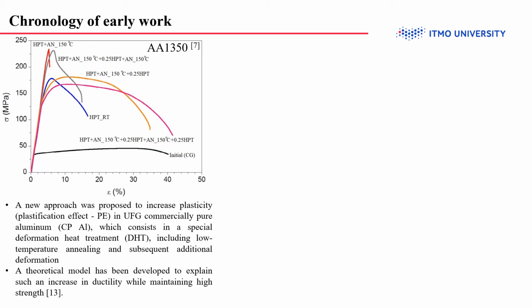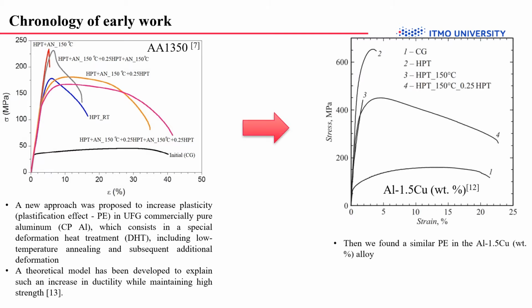According to this model, during the additional deformation, an additional density of extrinsic grain boundary dislocations is introduced into the structure of high-angle grain boundaries, relaxed after annealing, which leads to facilitating the emission of dislocations from grain boundaries. Then, a similar effect was found for aluminium-copper alloy structured by the HPT method. The next step was to study the effect of similar deformation heat treatment on the physical and mechanical properties of the new perspective UFG aluminium-copper-zirconium alloy.